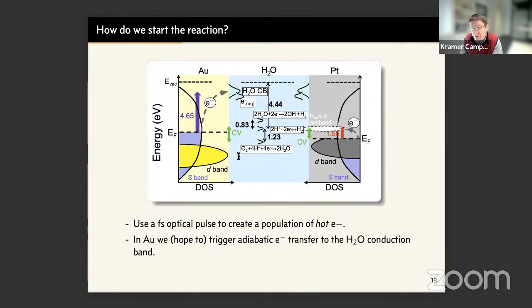Because gold is fairly inert, there are no surface states in this problem. And if we want to rapidly drive this chemistry, we need to do so by inducing adiabatic transfer into the conduction band of water. So the idea here is that we irradiate the sample with a pump pulse in the UV at 4.65 eV, and that this is sufficient now to promote electrons, some fraction of the electrons near the Fermi energy, and drive adiabatic transfer into water's conduction band.